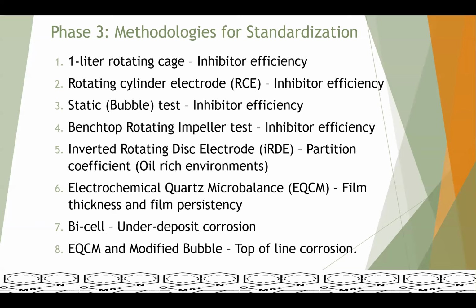In the industry, we use a film thickness value that was established in the 1940s and 50s. This was work that was done almost 60 years ago, but we do not have a quantitative method by which we can evaluate the film thickness, for which we identified the electrochemical quartz crystal microbalance. Some preliminary work has been done, but we'll be standardizing how the EQCM can be used to determine film thickness. We can also use the same EQCM to determine the film persistency. Film persistency may be important or will be important or is important for batch inhibition, for batch inhibitors.